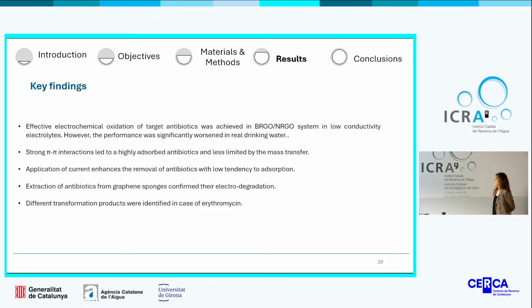The main findings of this study are that effective electrochemical oxidation of different target antibiotics was successfully achieved by doping the anode with boron and the cathode with nitrogen in low conductivity electrolytes. However, when we were using drinking water electrolyte, the performance was significantly worse. A strong π-π interaction leads to highly adsorbed antibiotics, and therefore they are less limited by mass transfer. The application of current improves the removal of all these studied antibiotics, even the ones with low tendency to get adsorbed onto the sponge. Then the methanol extraction confirmed the electrodegradation of the antibiotics, and different transformation products were successfully identified in the case of erythromycin.